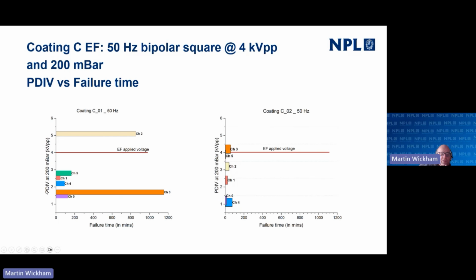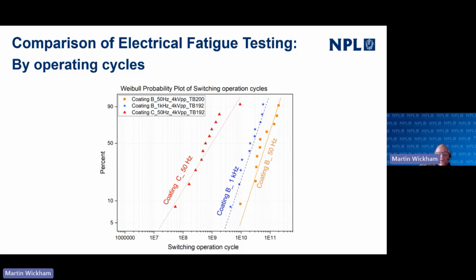And again, we can see here all of them mostly below the inception voltage, but there was one above and it still failed, and it wasn't actually the one that lasted the longest either. So if you start to plot these systems on the same graph, in order to compare frequencies and coatings, what we've done now is to look at switching operations as opposed to time to failure. So this is the time to failure times the frequency. If it's 100 seconds at 50 hertz, then it's obviously 5,000 switching operations. If it's the same at a kilohertz, then it's obviously 100,000 switching operations.